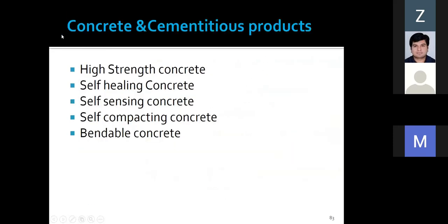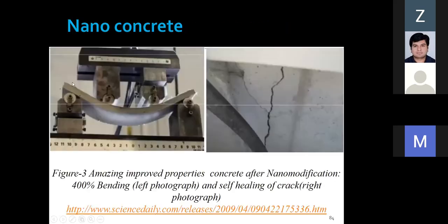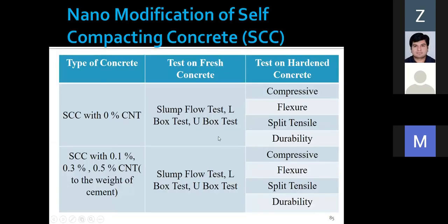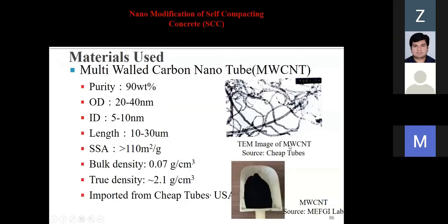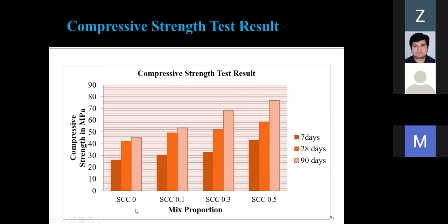Nano concrete is one which gives high strength concrete. It can be self-healing, self-sensing, self-compacting, and because of the nanomaterial present, it can be bendable also. At our university, our master students are working, and we were able to develop self-consolidating concrete. We tried 0.3%, 0.1%, and 0.5% carbon nanotubes, and we procured carbon nanotube. It is very costly, around 40,000 rupees per kg, right? And we applied them in the concrete, and the results are amazing.